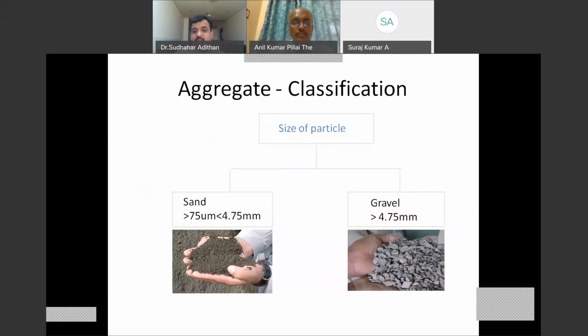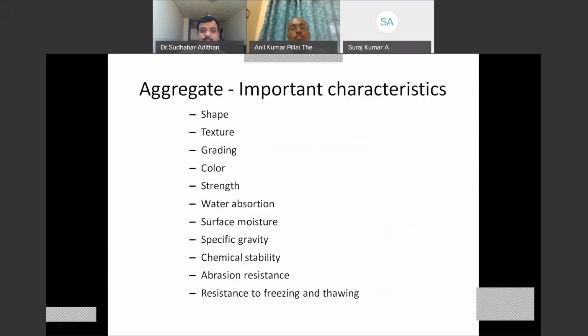If you have to stick to aggregate classification as far as concrete technology is concerned, then whatever is above 4.75 mm, you classify as coarse aggregate or gravel, and whatever is between 75 microns and 4.75 mm, you classify as sand. Even though purely you cannot take away minus 75 micron sizes from sand, generally a particle just below 75 microns and further down, you classify as clay or silt. It doesn't mean they will not be present in the sand system. They will be to a very negligible extent. So sand is basically between 75 microns and 4.75 mm.